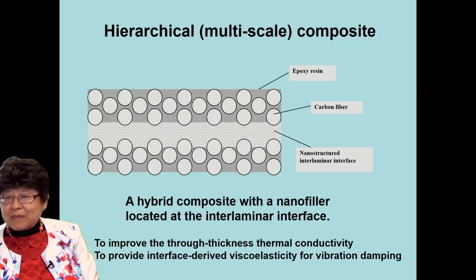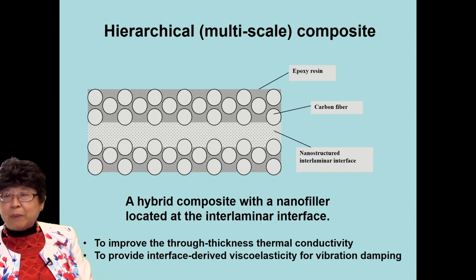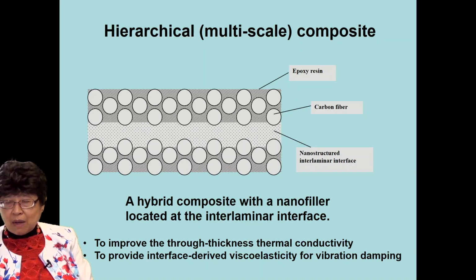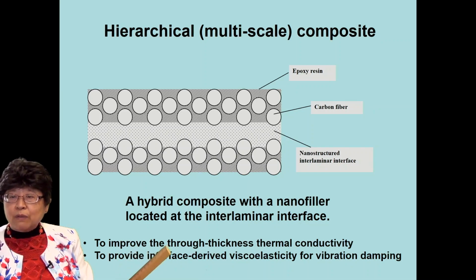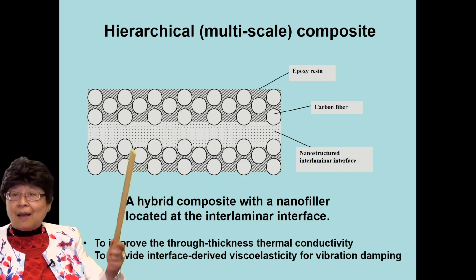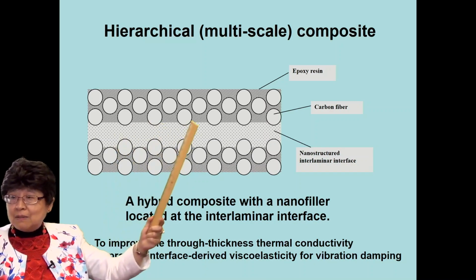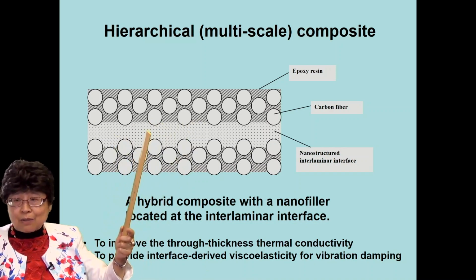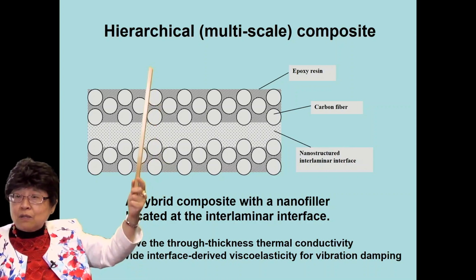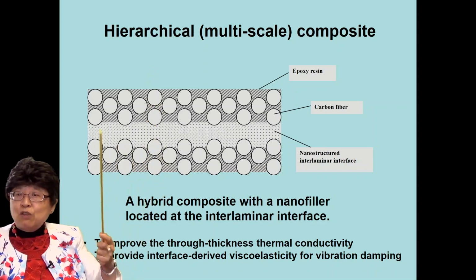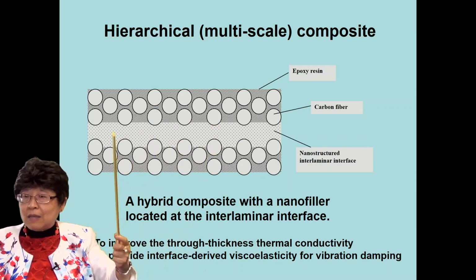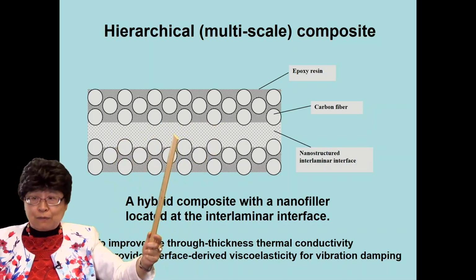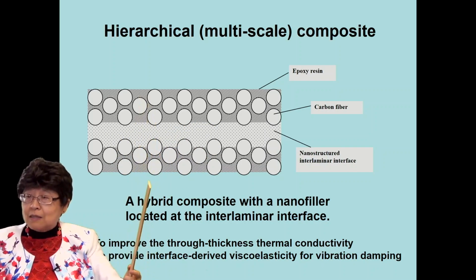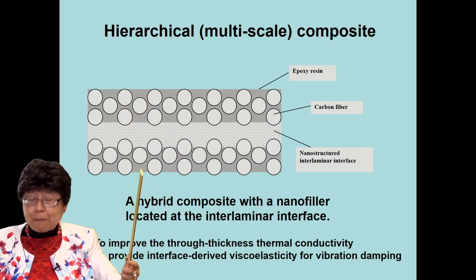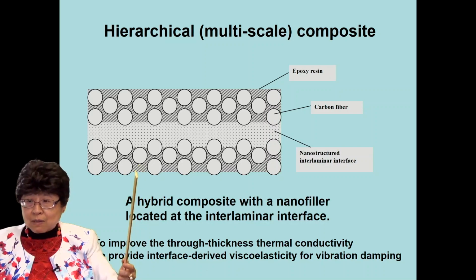Now, the reason why people like to have this hierarchical composite is twofold. One is to improve the through thickness thermal conductivity, because the polymer is a lousy thermal conductor, and because of that, the through thickness thermal conductivity is bad. But if you put in some nanofiller in the interface here, that's thermally conductive. It would help the thermal contact between these layers, thereby helping the thermal conductivity in the through thickness direction.